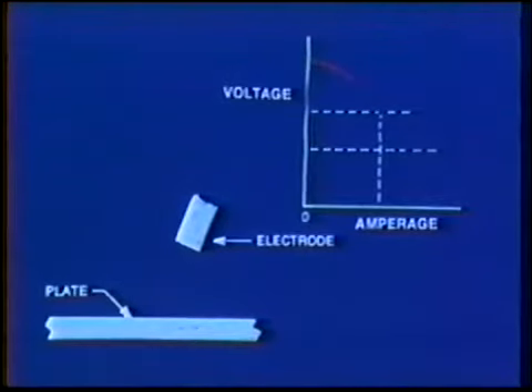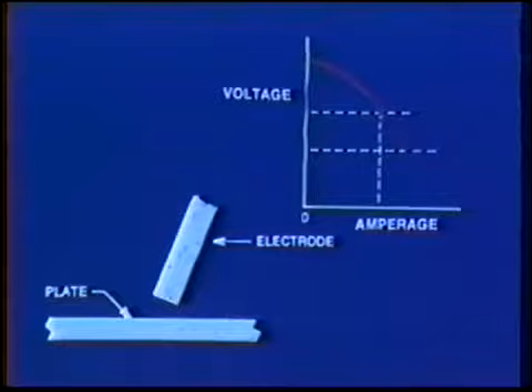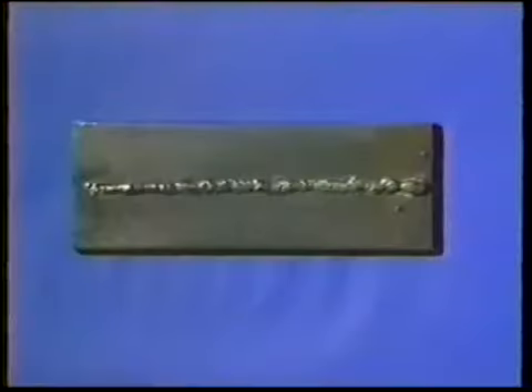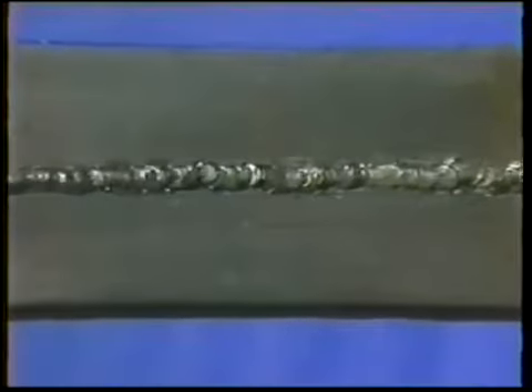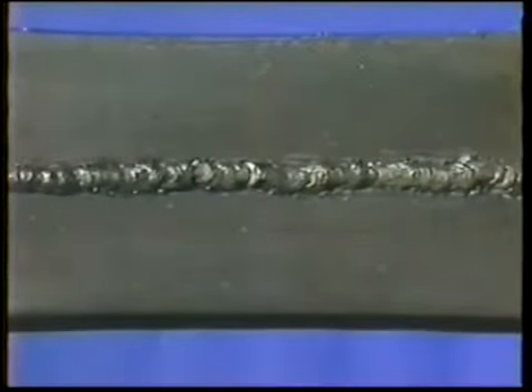Shortening the arc length reduces the voltage and increases the amperage slightly. If the arc length is too short, the arc will have a tendency to short out, and the electrode will freeze to the work. The weld deposit will be uneven and high with poor fusion. Slag and gas inclusions will normally result.